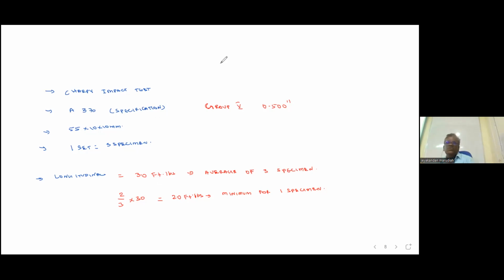So there can be different values, but what the code rule says, if the average is 30, minimum is 20. First point, one specimen below average. If one specimen goes below 30, that set is considered acceptable. So one specimen can go below average, but if 2 specimens go below average, that is rejected. If 3 specimens are below average, there will not be an average, so straight away it will be rejected. Second point is minimum: 1 specimen below minimum, reject.